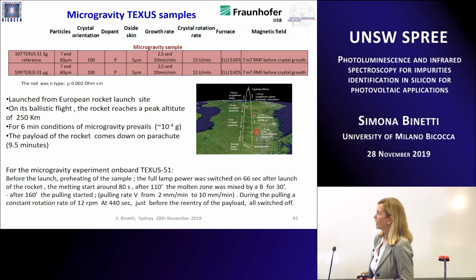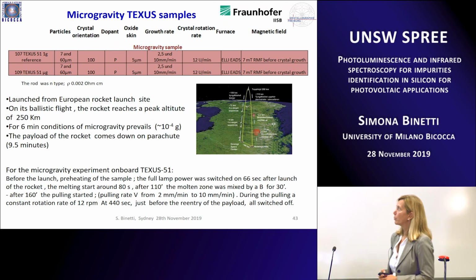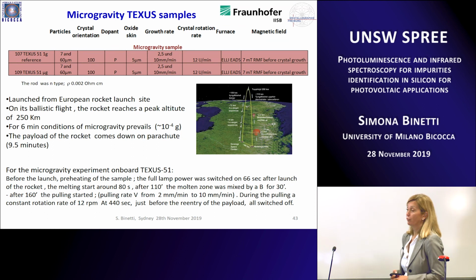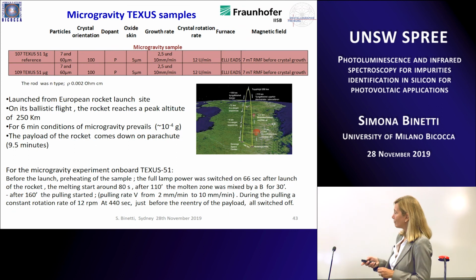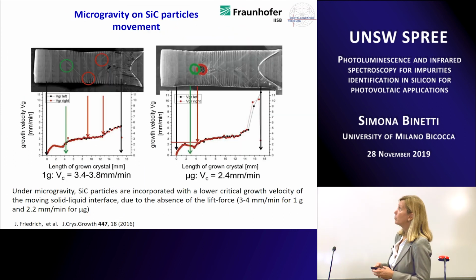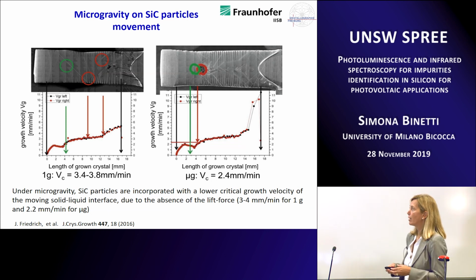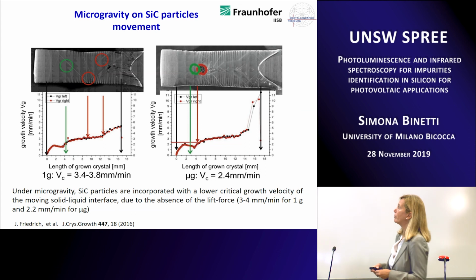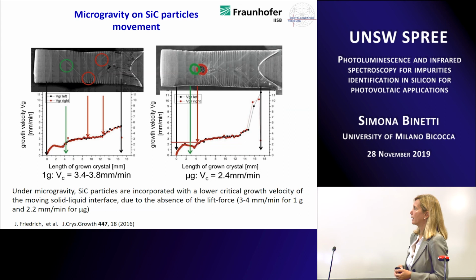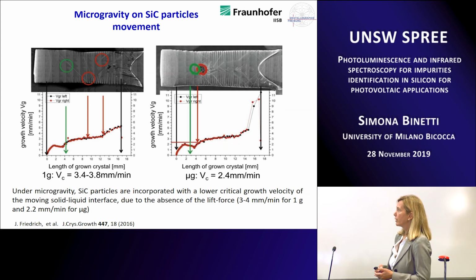And so it was launched from a European rocket launch site in Sweden, and then we have about 6 minutes of microgravity condition. So this is the reason why the ingot is very short. And at the end, we checked the movement of silicon carbide on this ingot grown in microgravity, and the German group found a completely different movement in comparison with the experiment on the ground, and it was as expected according to theory.